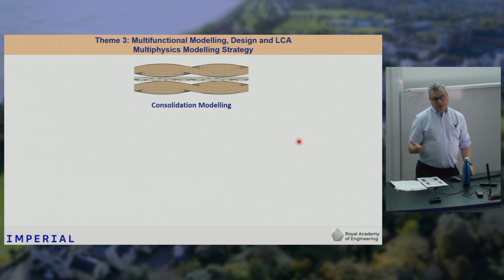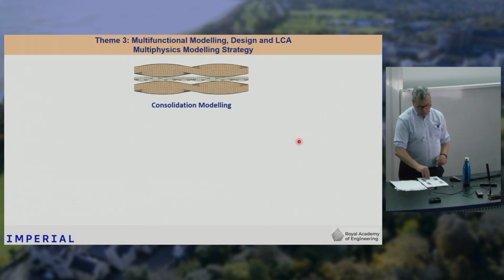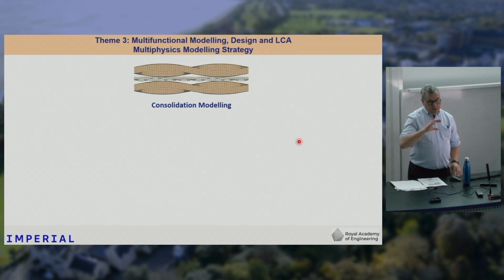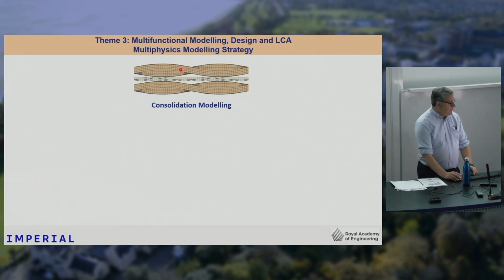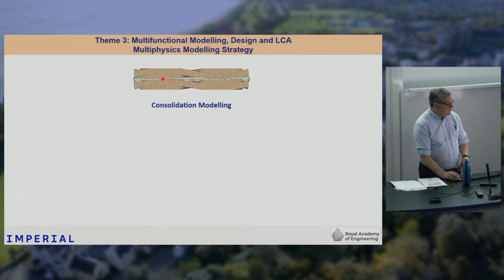Let me go up to a larger scale now and look at the sort of multiphysics modeling that we're trying to achieve. The idea behind this is that in order to get to the point where we can start to design our products using models, we need to have modeling tools in place. And we recognized early on that one of the first steps is modeling the consolidation process. So here you've got two electrodes and the separator, and then when you're consolidating those, I think the video should start, yeah. Then you're starting to squeeze those together and we start to see this effect, for instance, of nesting of the smaller weight of tow into the larger tow here.